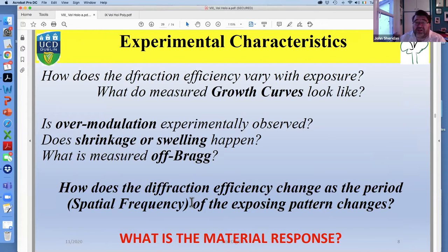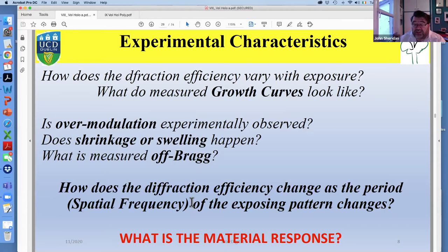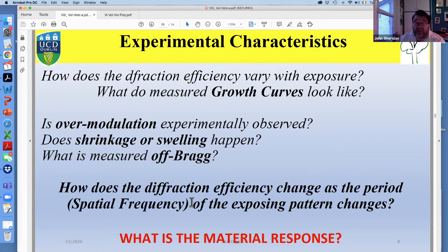I'm going to concentrate very much on photopolymers because they're the most popular type of material. There are a whole range of photopolymers — not just one type — sensitized in different ways to light. I'll talk about dyes and their advantages and disadvantages. For example, there are materials with very high glass transition temperatures, like PQ/PMMA, which can be used in solar concentrators in the desert. Other materials considered for holographic data storage would basically melt in the desert because they have lower glass transition temperatures — the temperature at which the material starts to flow.